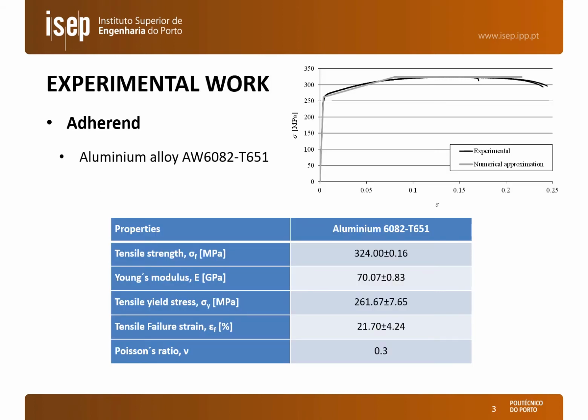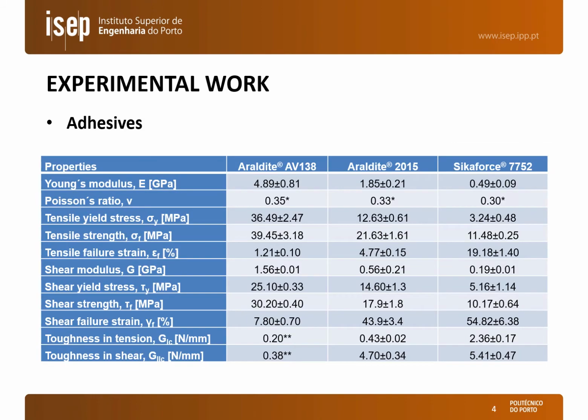Regarding the experimental work, the stepped bonded joints were made in a high strength aluminum alloy, AW6082. We can see in this figure the stress-strain curves obtained experimentally for this material, and also the simplified numerical approximation, and we also have a summary of some of the most important mechanical properties, such as the tensile strength and the tensile yield stress. We considered three adhesives to perform this analysis.